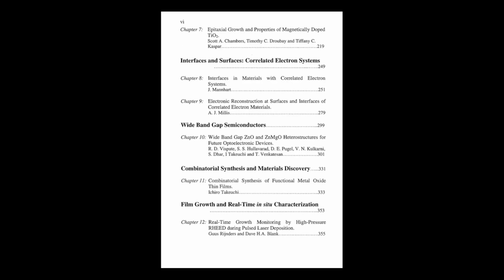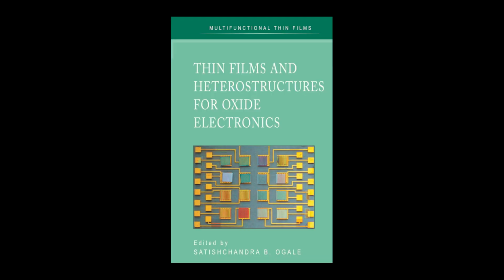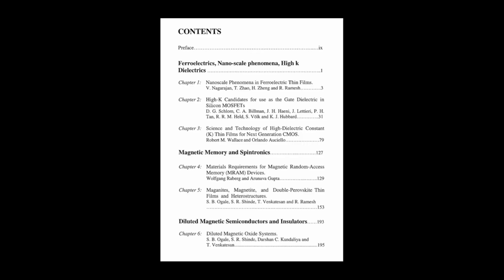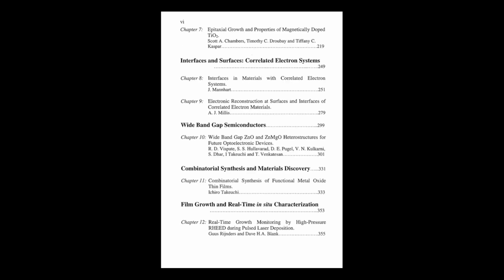1, obvious, right? High K value, much higher than 3.9, so you can get the same capacitance with a physically thicker layer, cutting down that tunneling leakage. Makes sense. 2, thermal and chemical stability in direct contact with silicon. This is huge. It has to survive the chip manufacturing process, including a critical high-temperature anneal, often around 900 degrees Celsius.